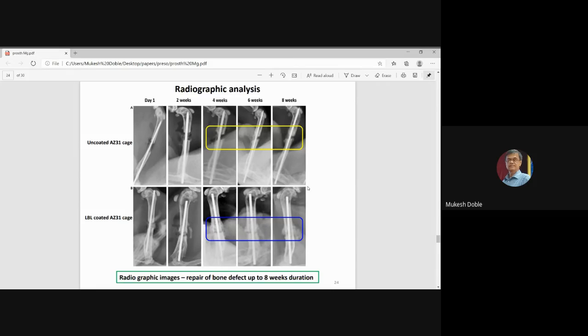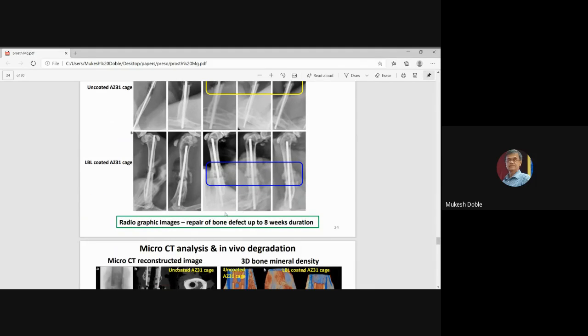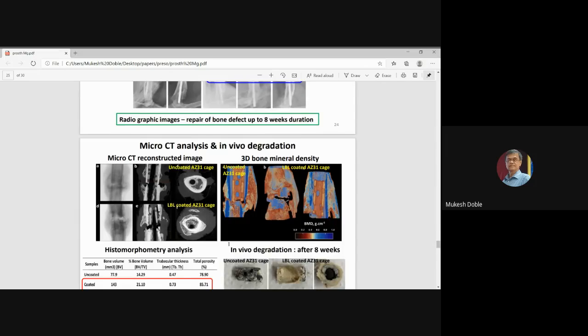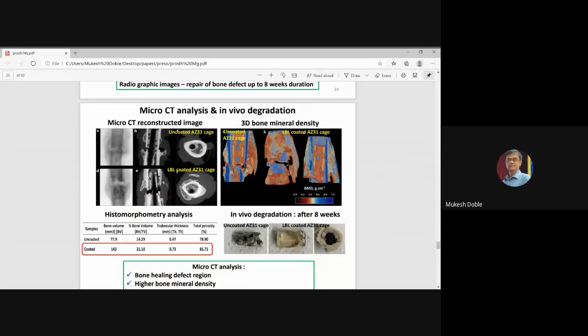Here we see the repair of bone defect within 8 weeks is happening from the radiography. Then we perform something called the micro CT analysis. The micro CT gives you an idea about the bone volume, percentage bone volume, as a function of time, and also the porosity. So this helps us to determine how the coated surface and uncoated surface perform with respect to each other. So we can look at the bone mineral density. This picture tells you the bone mineral density, with artificial colors just to see the density. So you can see the uncoated surface, and then you can see the coated surface.